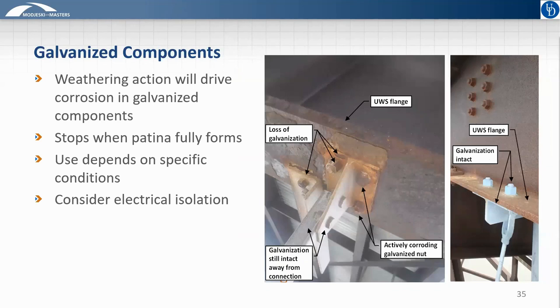And that happens to be with galvanized components attached to uncoated weathering steel bridges. The weathering action of the weathering steel does drive some corrosion in the attached component. During the formation of the patina, that will tend to accelerate the deterioration of the zinc coating on the galvanized component, but that tends to stop when the patina fully forms. So if you have areas that are not going to be frequently wet and you expect good and quick patina formation, then attaching galvanized components directly to the weathering steel shouldn't be a problem. If you have more exposed areas where it might take longer for the patina to form, then you're going to lose a lot of your zinc coating, and you should consider electrical isolation between the components with an isolation pad or similar.